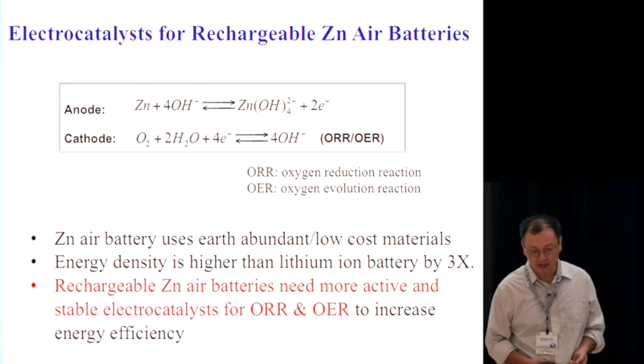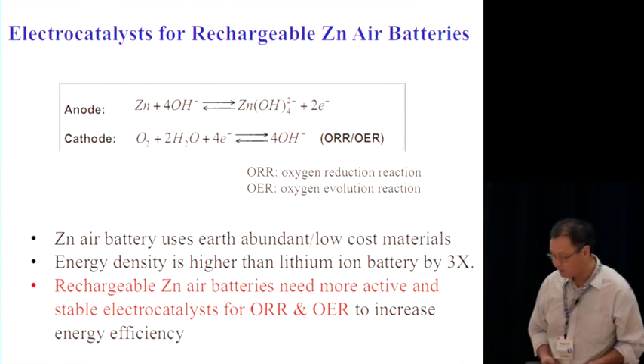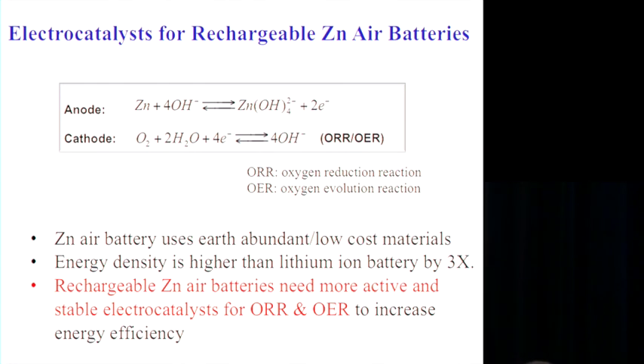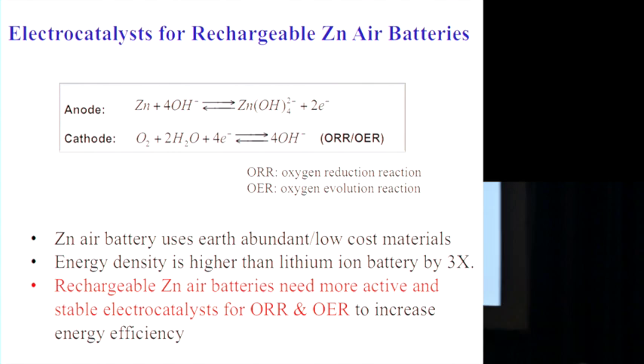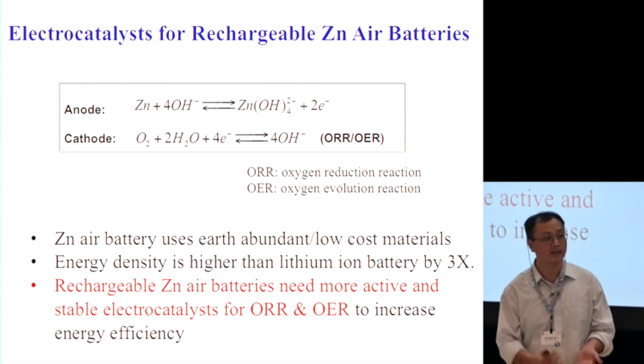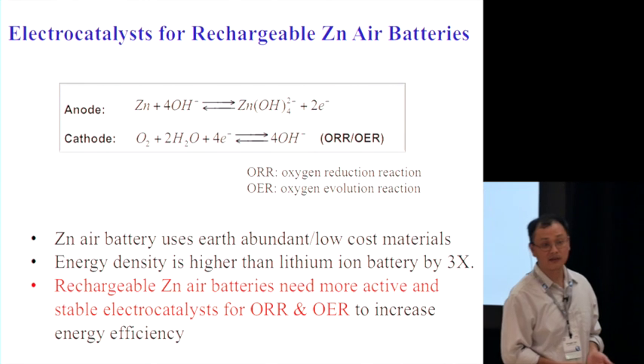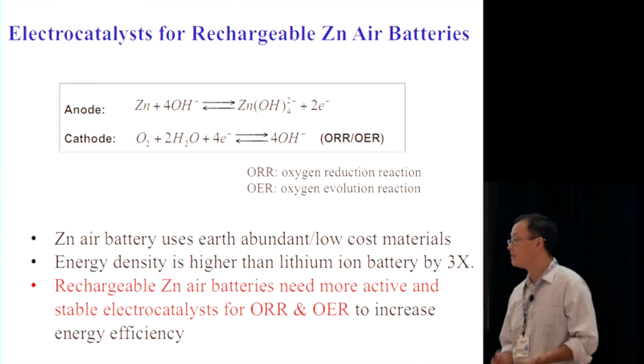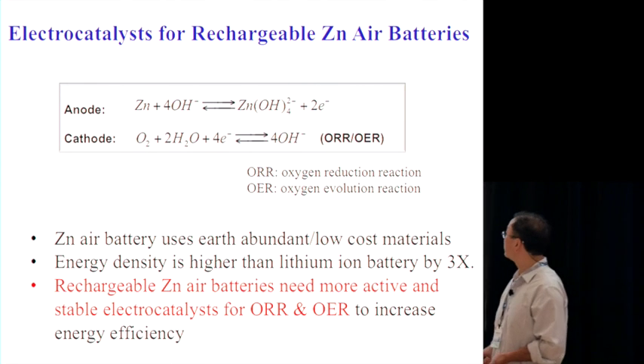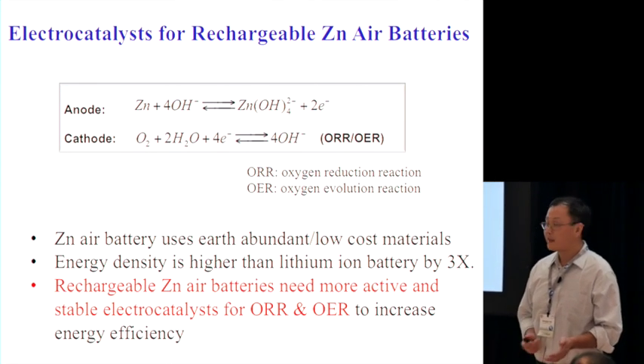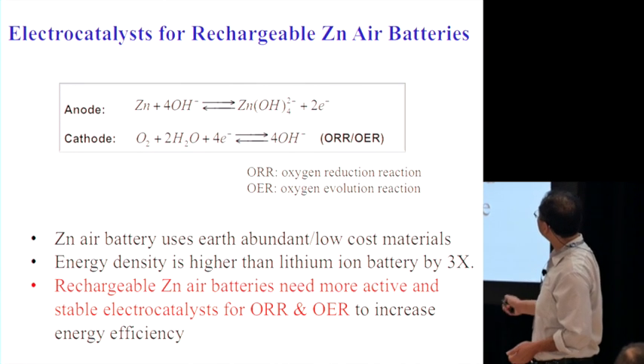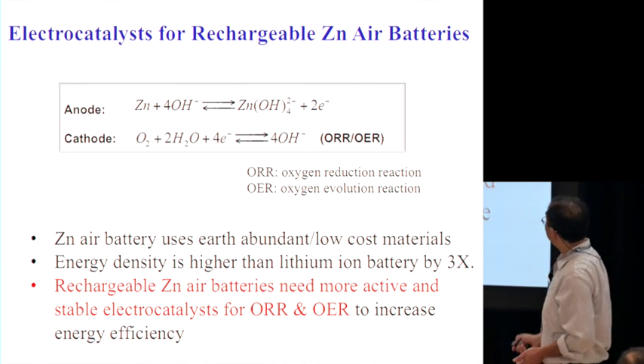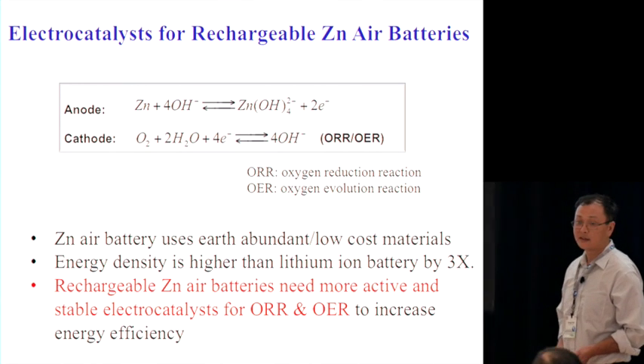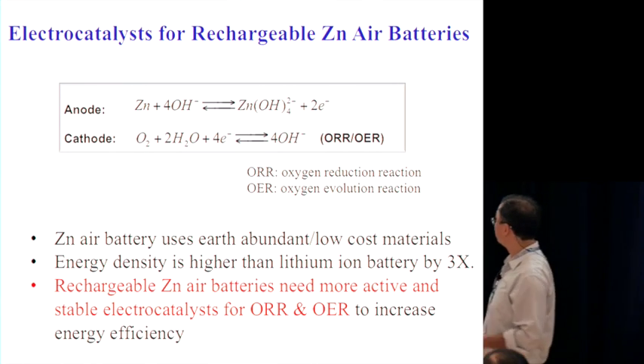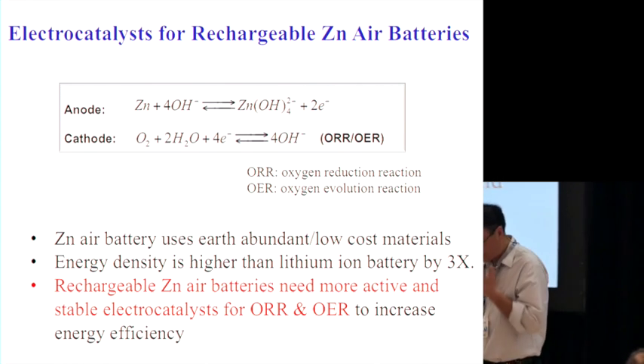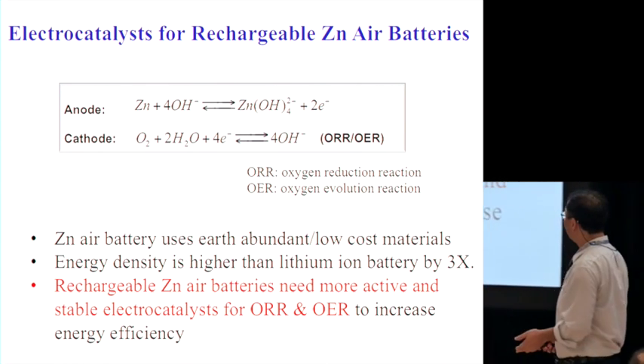One battery I want to mention is the zinc air battery, which is the one that is supported by GCEP. The reason we're working on the zinc air battery is that it has very high energy density, because if you oxidize zinc, you can get a lot of energy out. But the challenge is, can you make it rechargeable and can you make it energy efficient? There are a lot of issues with the zinc air battery, but what we worked on was the electrocatalysis side, because we have good electrocatalysts. So we use our electrocatalyst to increase the energy efficiency of a rechargeable zinc air battery.